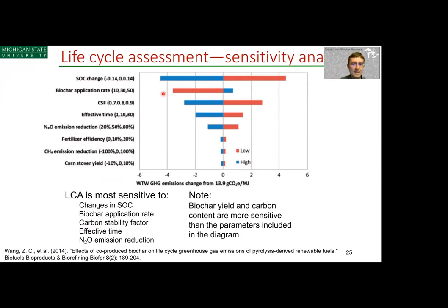This group looked at biochar application rate, and an interesting thing they found in the literature was that there are potentially positive priming effects of applying biochar to soils. If you add biochar to the soil, you might actually positively prime microorganisms to degrade neighboring or accessible soil organic carbon, so adding biochar might not necessarily be a good thing in all cases.